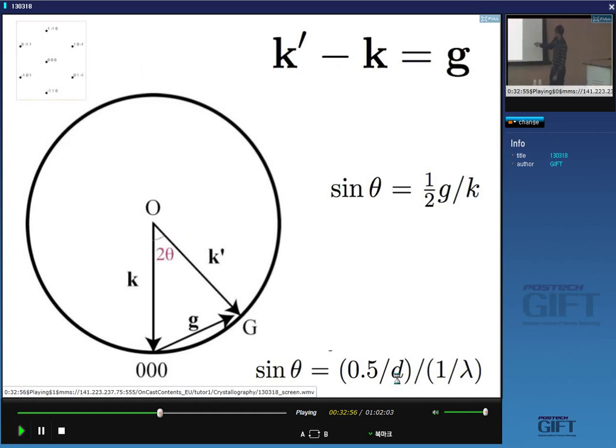Just drop a vertical line here and you'll see that sine of theta, opposite over hypotenuse, is half g divided by k, right? Substitute for g 1 upon d and substitute for k 1 upon lambda and we've got the Bragg law. So this is a vector representation of the Bragg law. Given that 2 theta is very, very small, approximately 1 degree, this angle here is almost 90 degrees, right? So when we look in a diffraction pattern, we are looking on this plane here, and the incident beam is almost at 90 degrees to that reciprocal lattice section.